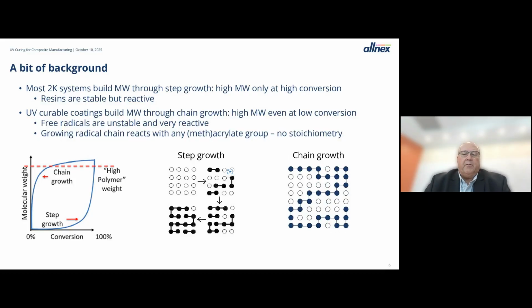And if we look at the difference, most two-component systems build molecular weight through a step growth process, and you only achieve high molecular weight or those good properties at high conversion. As you can see on the chart on the lower left, the step growth materials start out as monomers and then dimerize and then trimerize and take a long time to build up to that high molecular weight. So it takes a long time and high conversion to get to high molecular weight and good properties.